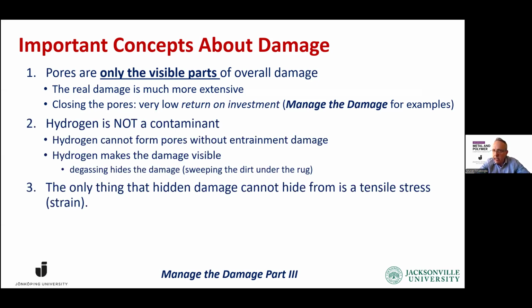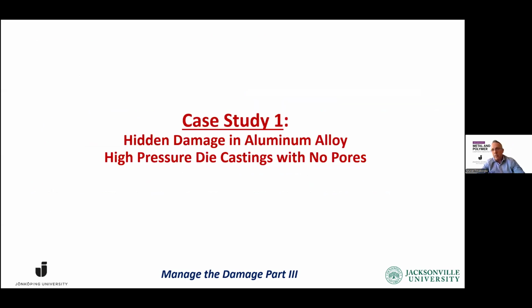Hydrogen is not a contaminant. Hydrogen cannot form pores if there is no pre-existing damage. All hydrogen does is to make the damage visible. So degassing hides the damage, sweeping the dirt under the rug. And the only thing that the hidden damage cannot hide from is a tensile stress or strain. This brings us to case study number 1. Jakob?